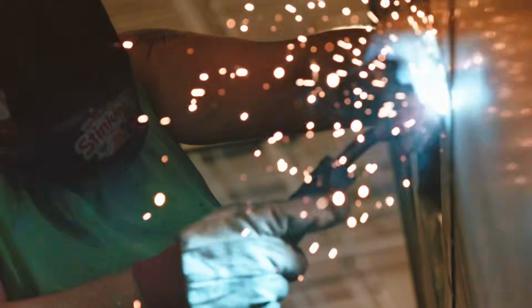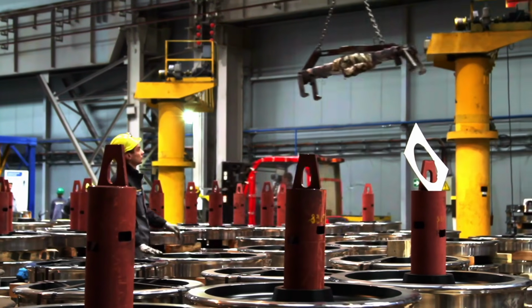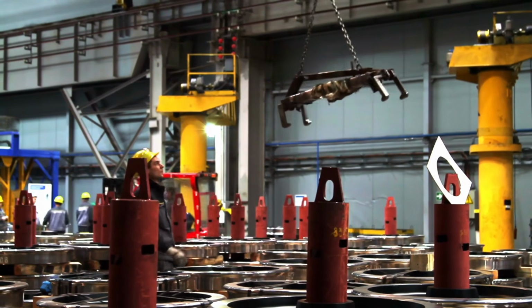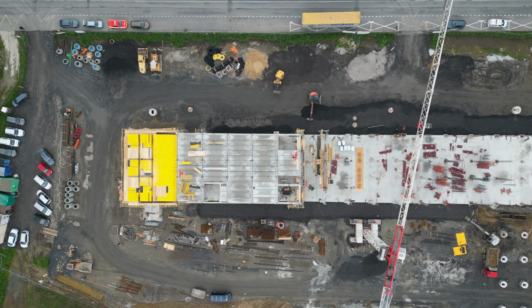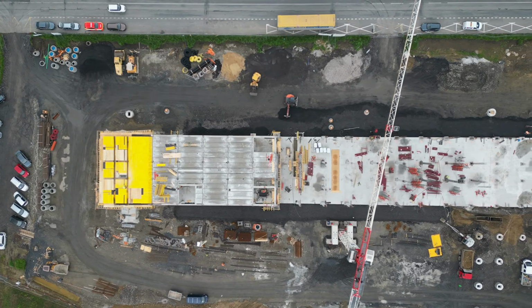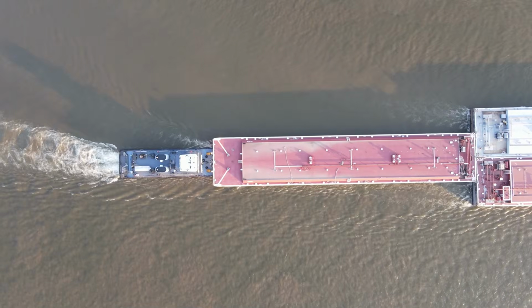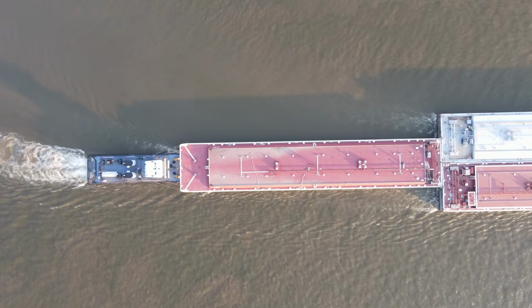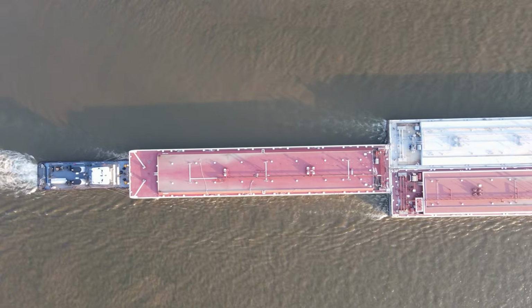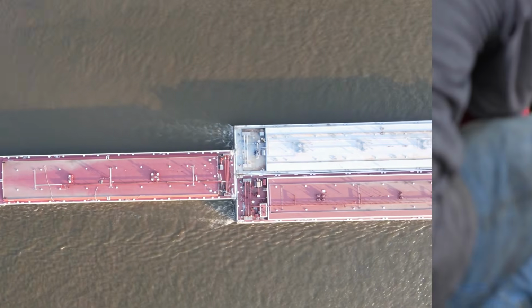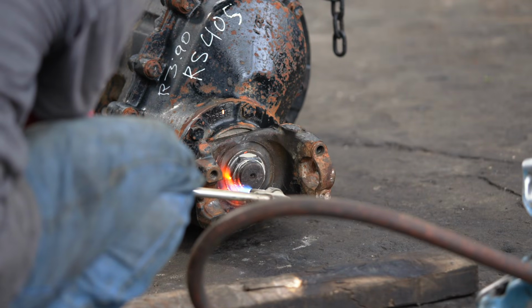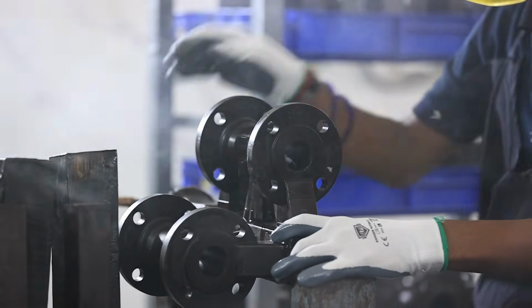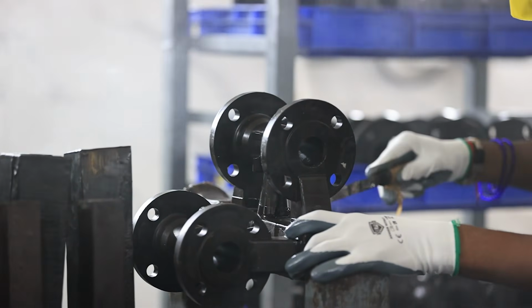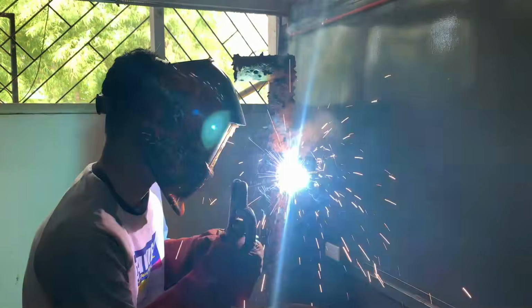A butt joint needs explaining because it is one of those construction details that sounds like nothing. Large ships are not built plate by plate. They are built as prefabricated blocks. Huge three-dimensional sections assembled in a hull, craned into the dock and welded together. The seam where two blocks meet is a butt joint, and it runs across the bottom of the ship. Everywhere else, that bottom plating is a continuous surface. At the butt joint, it is two surfaces joined by a weld, with the tolerances that implies: a slight misalignment between the two plates, residual stress locked in by the welding, and a small local geometric imperfection.